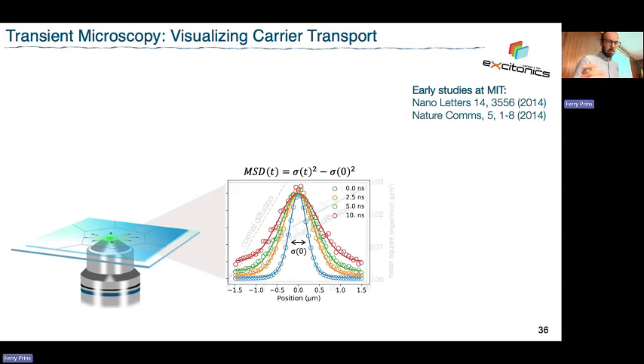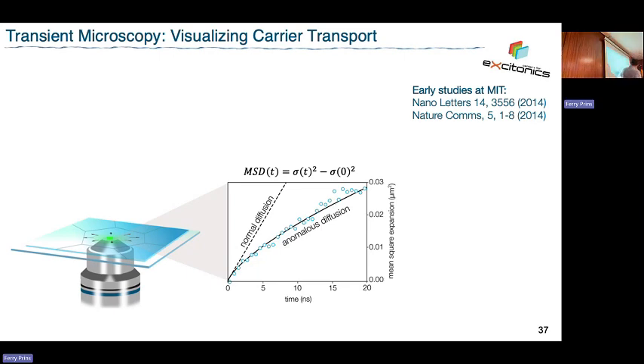You can plot that. What you get is, as a function of time, mean square expansion - how fast does your population broaden in time? Now, if I would have normal diffusion, just like random walk diffusion, I would get a straight line here - the Einstein relation. And that straight line, the slope of that, would give me my diffusivity, proportional to the diffusivity of my material.